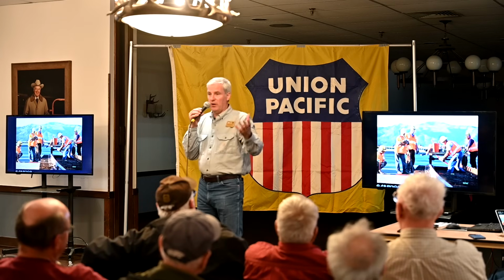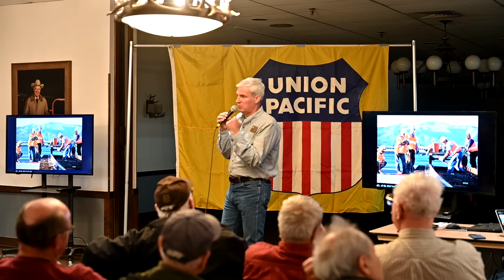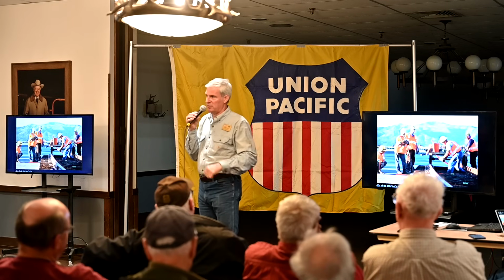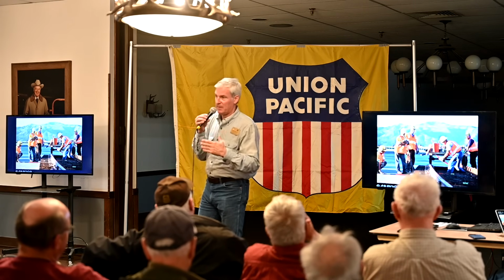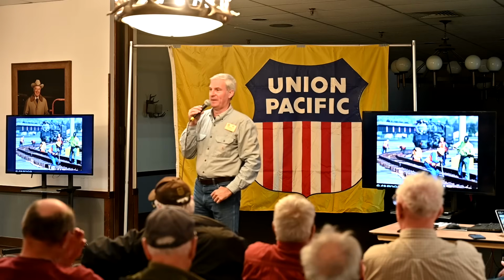That may just be a number, but 1045 is like a good medium carbon bolt, a good solid bolt. 1008 is a very low carbon, stable rivet. And we did some work and the rivet head blew off. Well, that shouldn't happen. So anyway, that's how we discovered that. Good question.